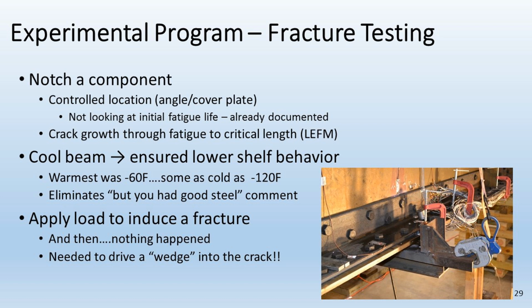Excellent question. So in AASHTO, in the U.S., we have different temperature zones. We have different lower temperatures that we design for, zone 1, 2, and 3. A bridge in South Texas is treated differently in material requirements from a bridge in North Dakota. However, the reason we do that is because of material toughness, or its ability to tolerate a fracture, to tolerate a crack, or to prevent a crack from initiating. Say, in the case of a built-up member, one component fractures suddenly, there's the bang as you hopefully heard in the video. What we don't want is the second component to fracture.